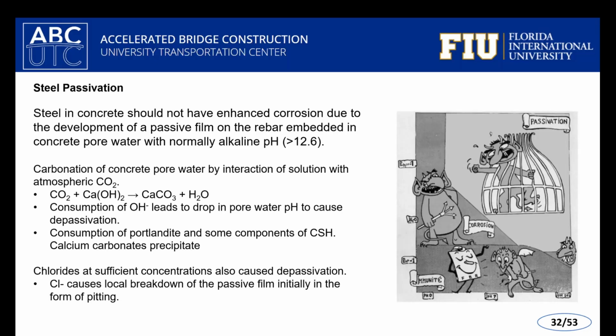So ideally, steel placed in concrete environments should be a very ideal situation. Steel in the high pH environment in the concrete pore water typically develops a passive film, really corrosion should not occur at all. But it's in extreme environments and aggressive environments where that passive film can be broken down. And most of the cases that we see, especially from marine bridges and marine columns as well, and other environments, it has to do with the presence of salts.